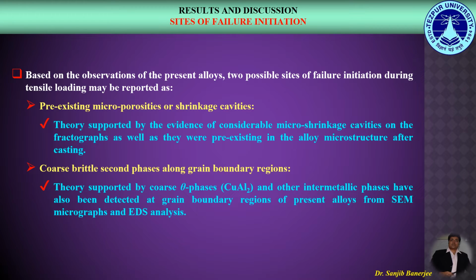Based on these observations of the present alloys, two possible sites of failure initiation during tensile loading were reported: firstly, the pre-existing microporosities or shrinkage cavities which were formed during the solidification or casting itself, and secondly, the coarse, brittle second phases along grain boundary regions. Now, this theory was supported by the presence of coarse theta phase, chemically CuAl2, and other intermetallic phases which have been detected at the grain boundary regions of the present alloys from SEM micrographs and further from the EDS analysis.